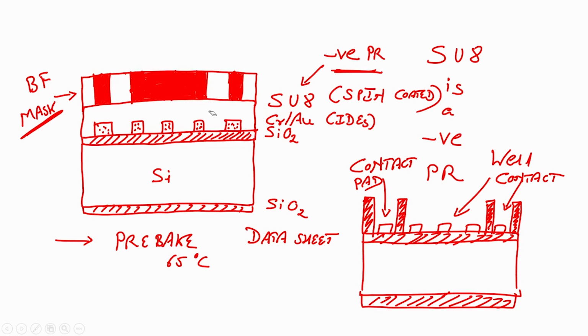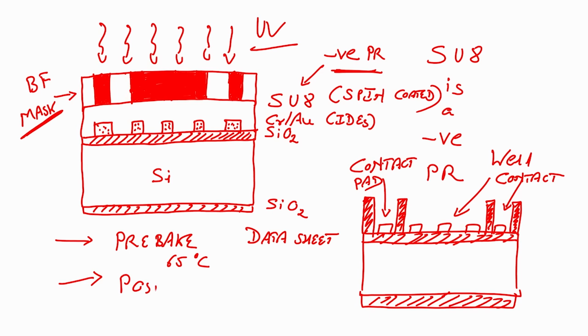Now let me repeat, the property of the negative photoresist is that if you use a bright field mask, whatever the pattern on the mask, the reverse will come on the wafer. So that means let me expose this wafer with UV light. Then what will happen after exposure? After exposure, in the case of SU8, the manufacturer tells us to post bake before you develop it. Post bake is done at 90 degrees or 95 degrees.